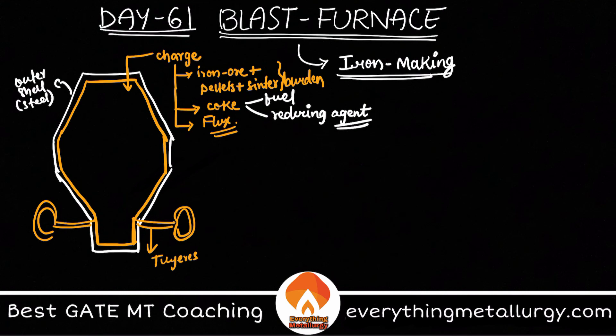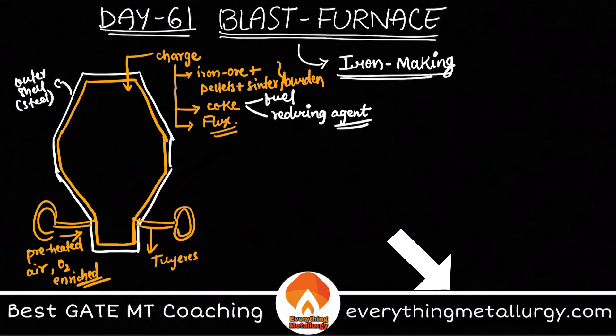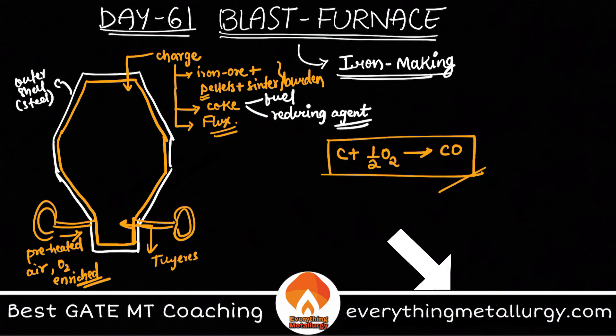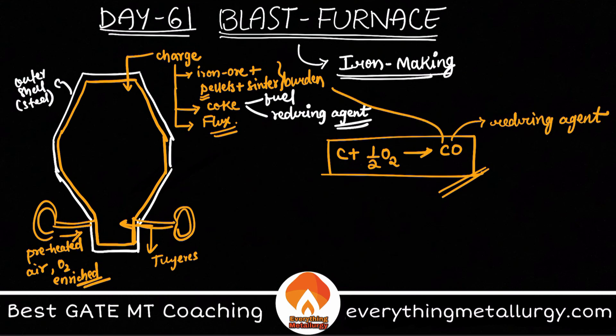Air is inserted using the tuyeres. We inject preheated air which is oxygen-enriched inside the furnace. Here, the coke reacts with the preheated air — carbon combusts and CO is formed. This CO is the reducing agent, which reacts with the burden and reduces the ore particles. This reaction is also exothermic.